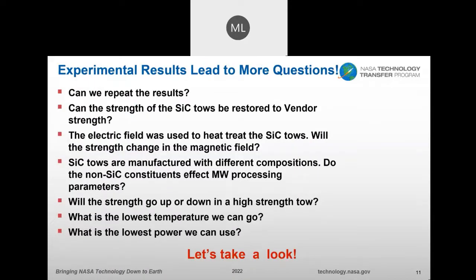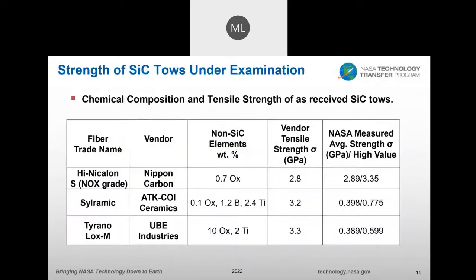So this led to a lot of questions. Can we repeat the results? Can the strength of the silicon carbide tows be restored to vendor strength? The electric field was used in the heat treatment of the silicon carbide tows. Will the strength change in the magnetic field? The silicon carbide tows are manufactured with different compositions, so do the non-silicon carbide constituents affect the microwave processing parameters? Will the strength go up or down in a high strength tow? And what is the lowest temperature we can achieve? And what is the lowest power we can achieve? So let's take a look. Next slide, please.